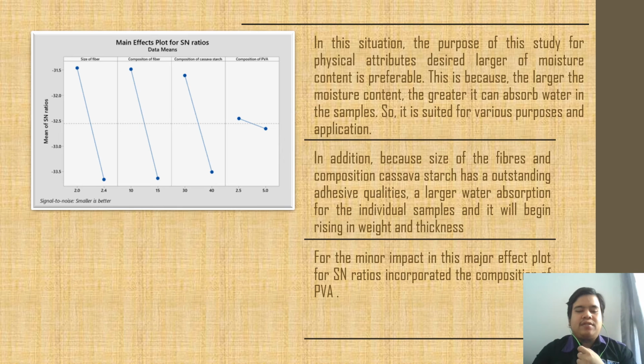In addition, because the size of the fibers and the composition of cassava starch have outstanding adhesive qualities, there is a larger water absorption for the individual samples, and they will begin rising in weight and thickness too. After that, the minor impact in this main effect plot for signal-to-noise ratios was the composition of PVA.